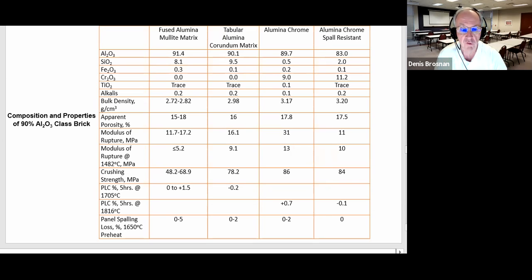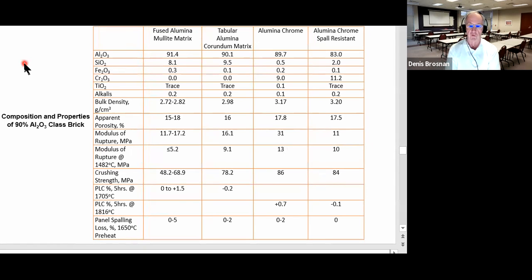The way this was explained to me by a professor a long time ago was when they first came out with automobiles, a Model T Ford. If you had a crack in the fender and couldn't do anything else to fix it, you couldn't weld it, then you could bore a hole right at the tip of the crack, and that would blunt the crack tip and stop the progression of the cracking. And that's kind of the idea in improving the fracture toughness of alumina by increasing the fine pore fractions.